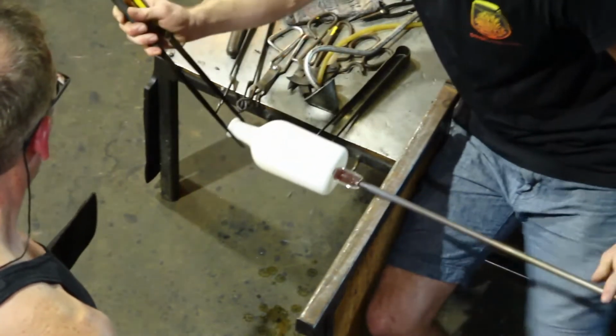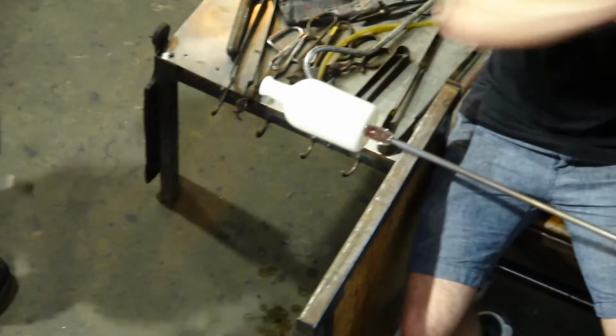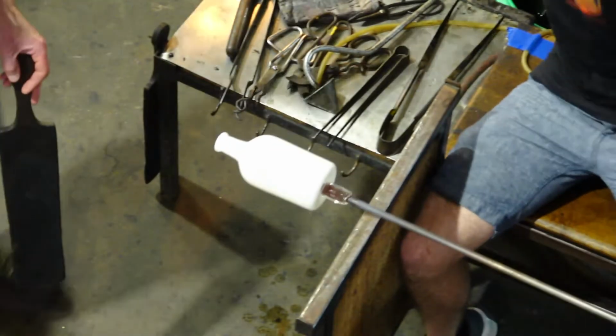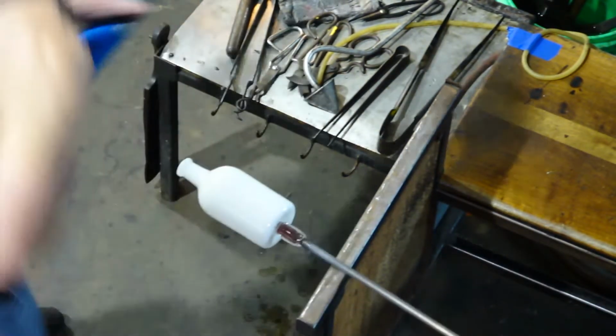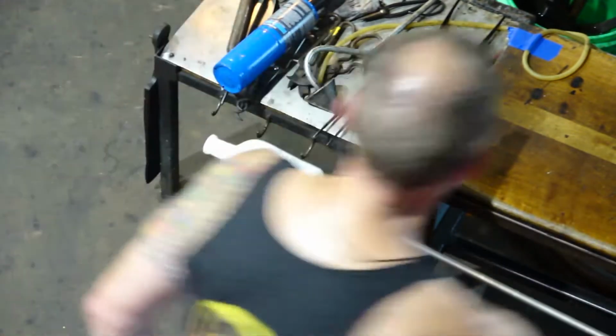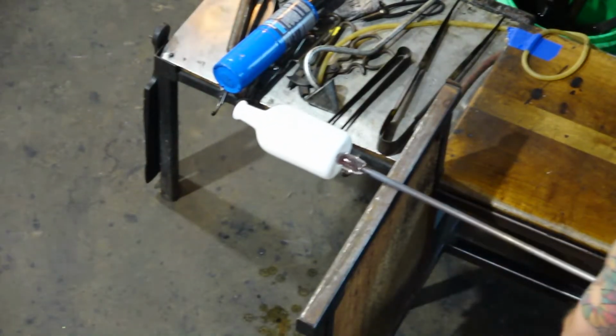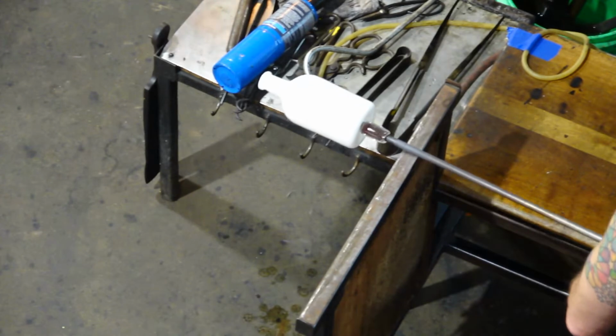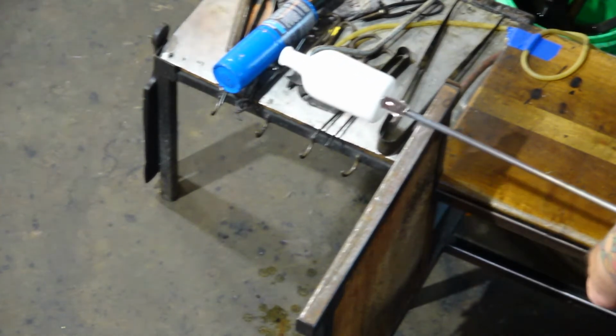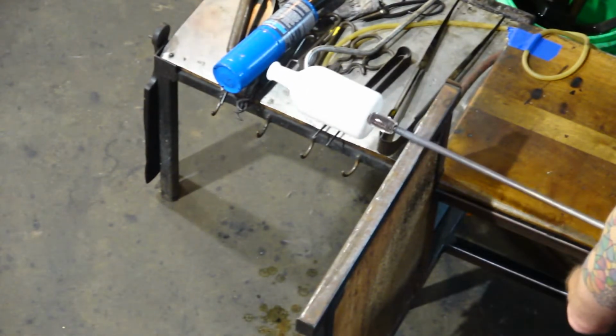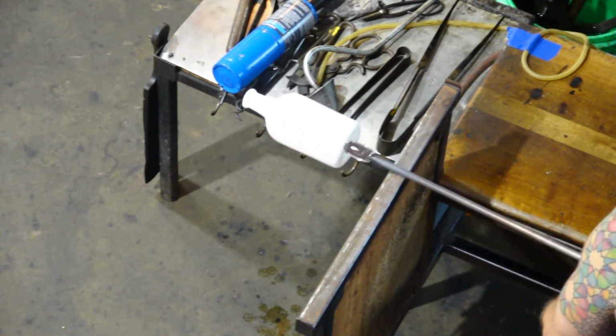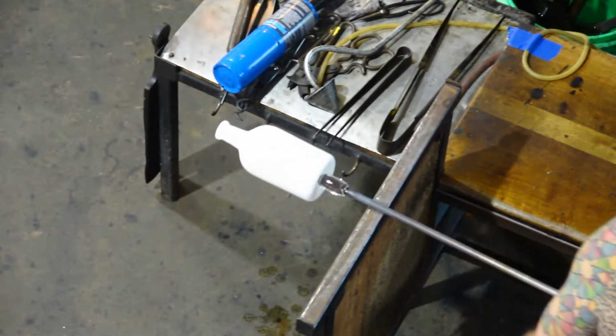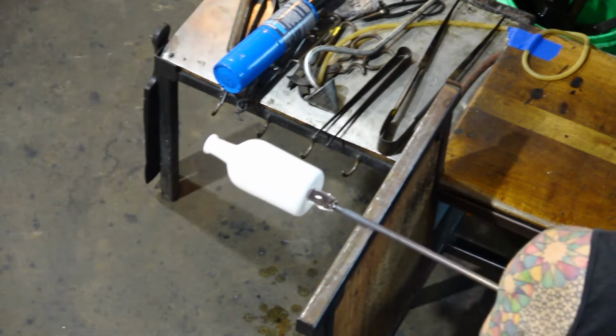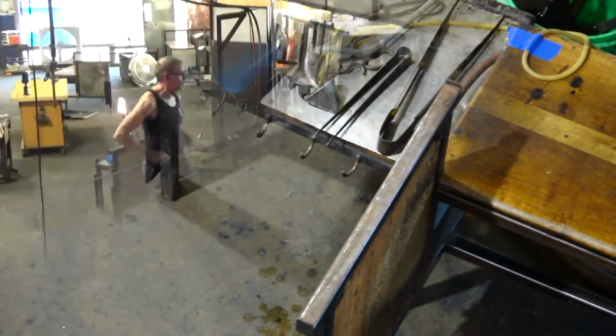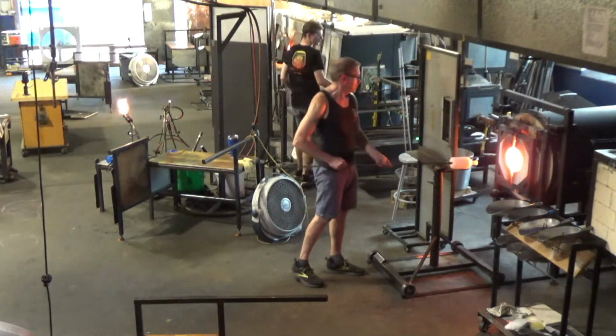How long it takes to come down depends on how much work is in there, because there's a lot of heat in there as we load it. So if it's hotter, it takes longer to cool down, because that heat has to dissipate over time. But the computer controls it at a rate to make sure that the heat inside the glass can get all the way to the edge, and it only comes down a degree or two different from the outside and the inside. So the thicker the glass is, the longer you have to let it cool. Sometimes we have artists who will make really heavy paperweights or really thick glass, and they'll set it to come down over 3 days.